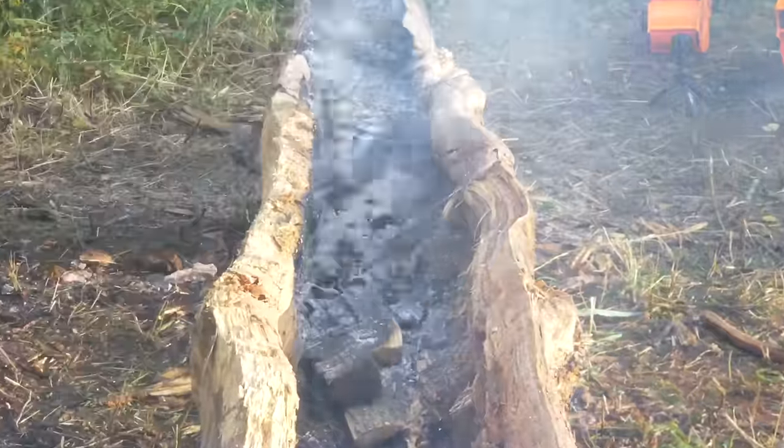Getting the bronze fully melted took several attempts with small batches, and even then it proved to be difficult to get it to cast before it would cool and solidify. Yeah, like sparkles. For molds for the casting, I tried using dried clay, but we quickly learned that they still contained too much water that would cause some less than ideal results. I then switched to using sand for the mold.